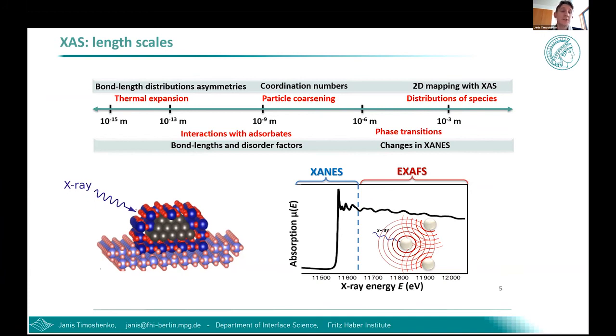So what's important here, and what is actually a very nice advantage of X-ray absorption spectroscopy over other techniques, is that from a single experimental measurement, we can get quite rich information about the structure and properties of our catalysts. So we can look at quite subtle things such as changes in interatomic distances due to thermal expansion or due to interaction of metal atoms with adsorbates. Or from the same data, we can also look at nanoscale structure of the catalyst and look how particle sizes and shapes change under reaction conditions. And of course, we can look also at the bigger picture, how crystallographical phase or oxidation and reduction happens, which involves the entire sample. And finally, when we couple XAS with spatially resolved data acquisition methods, we can use X-ray absorption spectroscopy to map distributions of different species within our macroscopic chemical reactors. So a lot of possibilities here for studies of catalysts.